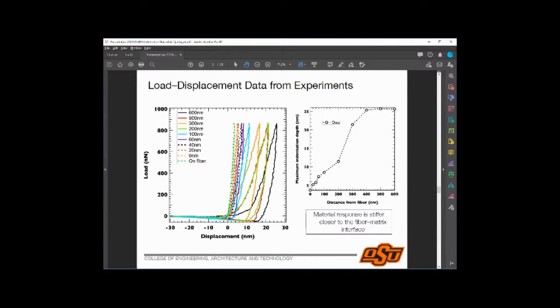Professor, you said about the swelling of the composite. Would that change the weight? Would that swelling degrade, would it damage the fiber or the matrix after 1 hour of the UV exposure? You showed us in one slide that there is a sinking of the load after 1 hour of UV exposure, and then it would increase after 6 hours. I have a little bit of doubt, because I believe when the damage happens after 1 hour, with the load transfer, would the fiber just take the load? But there is no interface between fiber and matrix, because the matrix has been damaged already after 1 hour.